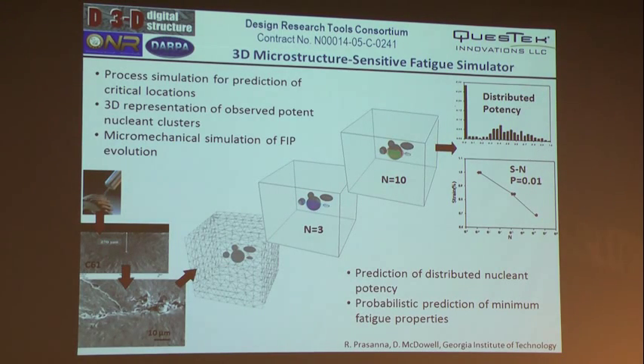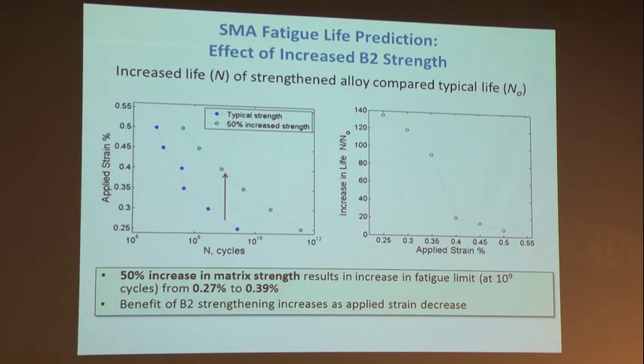And here's an example where we have built out during the D3D project a micromechanical fatigue nucleation simulator, which we've demonstrated in the steels. We're now doing the same thing in the shape memory alloy. And here's an example of the predicted improvement in allowable strain amplitude we can get at a life of 10 to the 9th, which is very hard to measure. The kind of improvement we can get by getting a 50% strength increase by bringing in nanodispersion strengthening into these shape memory alloys.